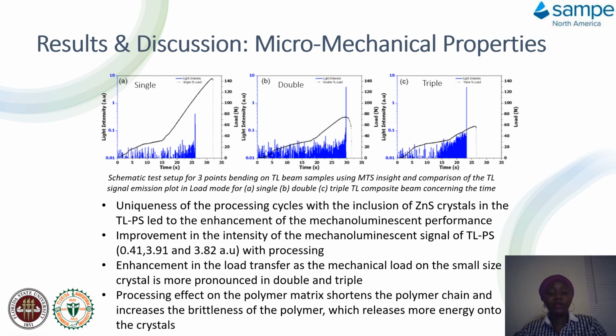After carrying out the thermal analysis, we carried out a 3-point bending test. This 3-point bending test is for us to show the MTS, the mechanical test system, to compare the TL signal emission from the 1st, which is single, to double process to triple process. And you can see right here, the uniqueness of the cycle is that as the processing increases, the emission increases without much load.